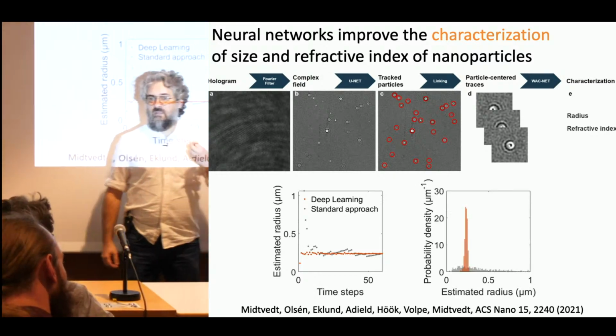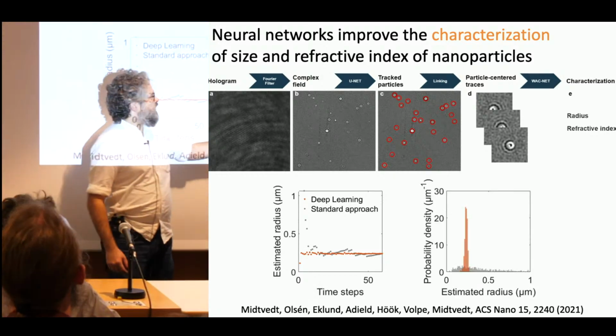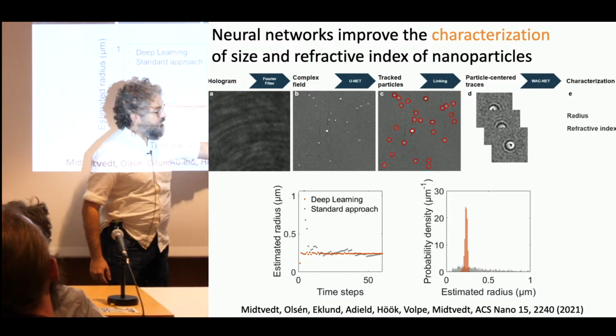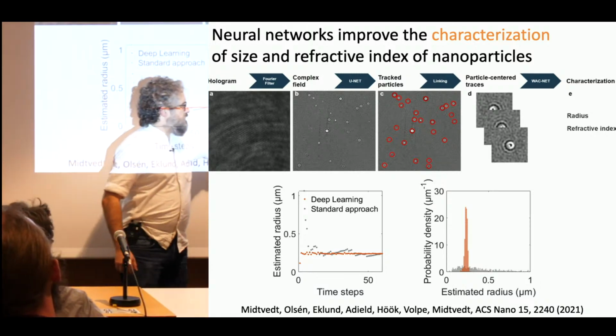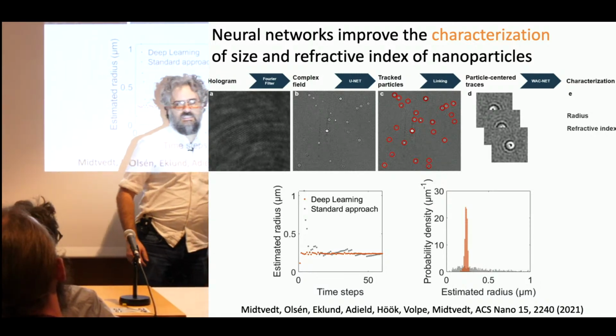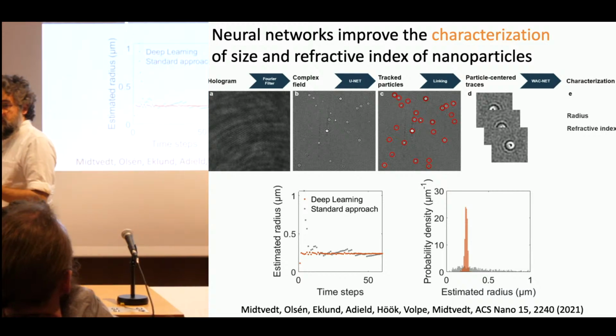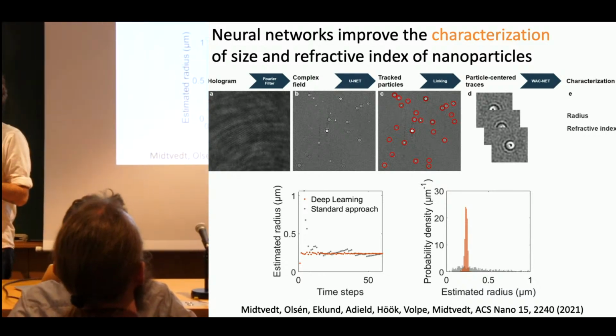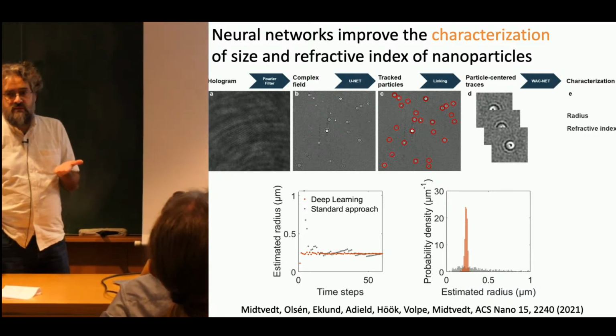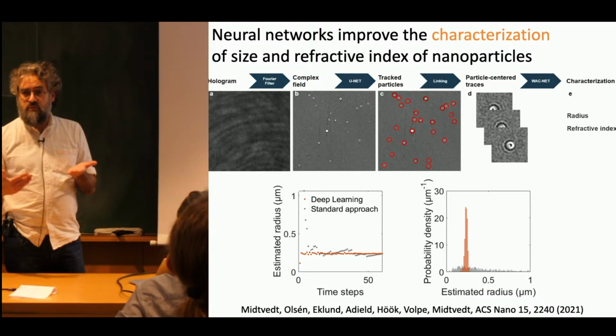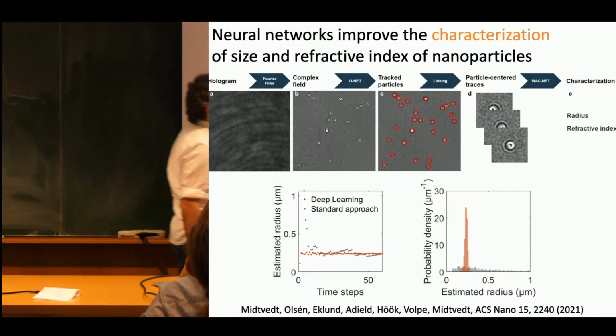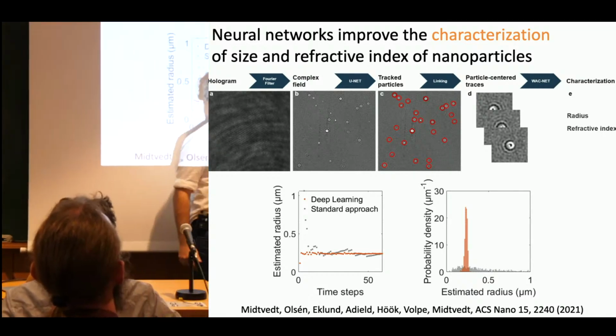We get, in this case, the probability density of the radius estimated by the neural network. And here is the same radius estimated from the diffusion. Since we have a small video of the particle diffusing over a few frames, we can calculate from the diffusion, which would be the standard method. And you see the neural network does incredibly much better.